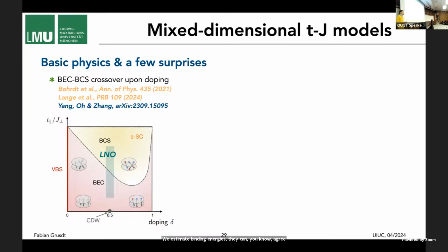Okay, now the reason this is relevant to these new LNO high Tc superconductors is that these systems are believed to be around 50% doping. So these orbitals, they should be 50% hole doped. That's quite a high doping. So it's not obvious that this simple string-like picture that I developed at low doping should apply. And in this review that I mentioned, that's a review, but also has some things we thought were interesting. In it, we looked at this and we actually said, oh, probably there's some BEC to BCS crossover. And it turns out these LNO superconductors, they should be somewhere here, close to this BEC to BCS crossover.